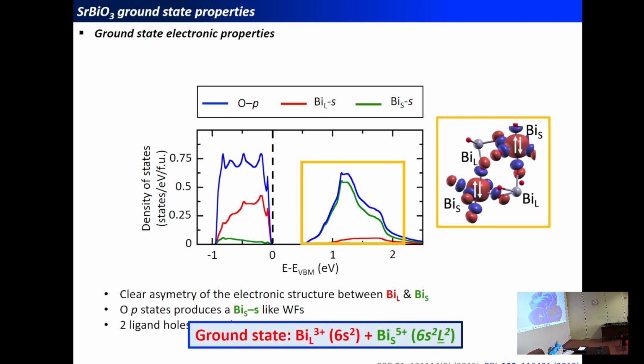So the one that is sitting in the extended octahedra is really occupied with two S electrons. And the small bismuth cation is in a 5+ oxidation state, but what we have is two ligand holes that are in fact created on the surrounding oxygens. So the surrounding oxygens are just giving back some electrons to the bismuth cation, and the two holes that should be created through the charge disproportionation are just spread on the surrounding oxygens instead of really being centered on the bismuth cation. So in this compound, we really have a charge ordering that is appearing with bismuth 3+ and bismuth 5+ cations.